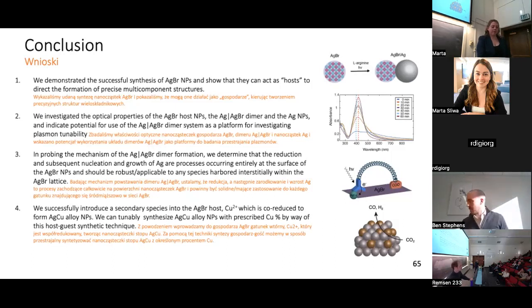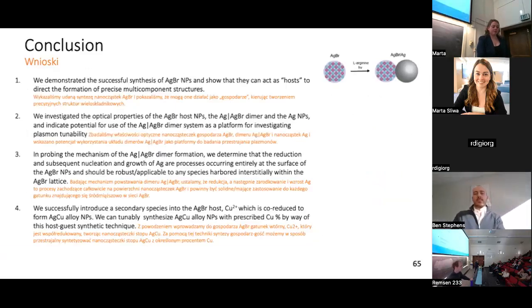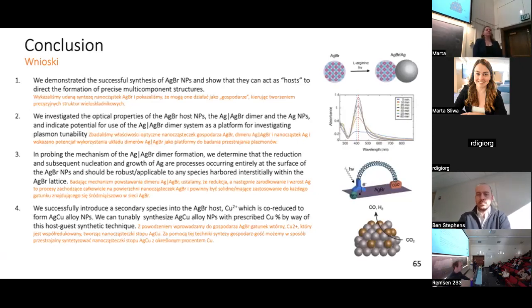And then, backwards: when you make the so-called silver bromide, silver dimer, you're reducing it and adding reductant. But the silver solid, the metallic zero-valent silver, comes at the expense of silver ion in silver bromide. Correct. So isn't there a loss in size of the left hand side as the right hand side gets bigger?